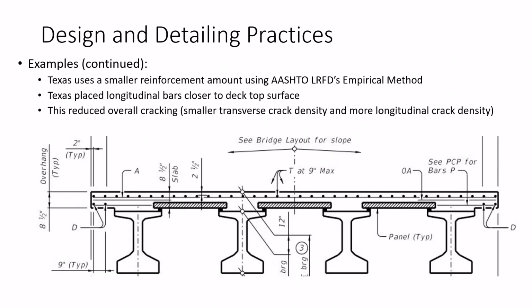Texas DOT talked about how they reduce the amount of reinforcement in the decks as a method of reducing cracking. That may sound counterintuitive, but their reasoning is that with a smaller amount of reinforcing, the corrosion product that builds over time will be small, and that will create less pressure when it expands and result in less cracking.